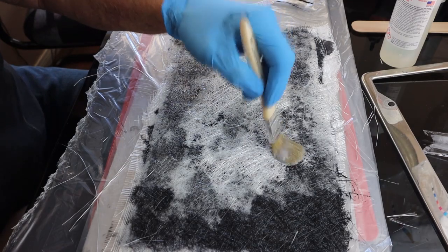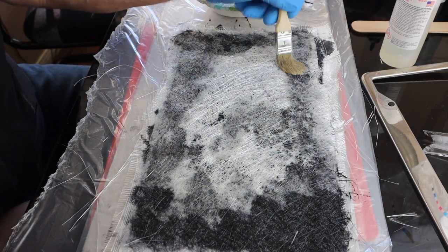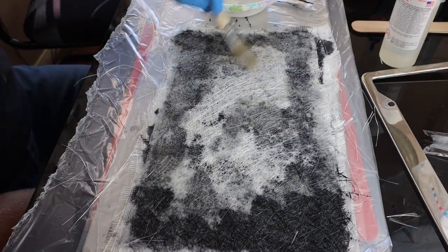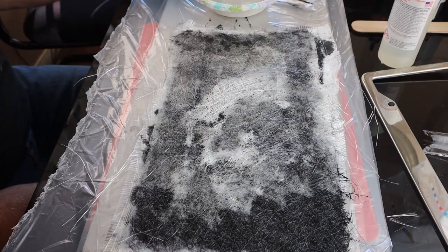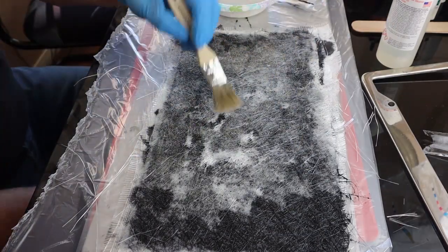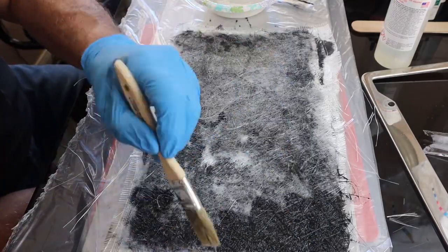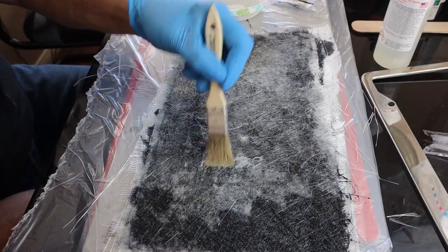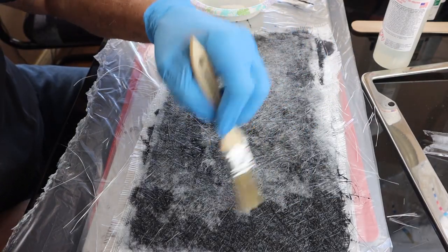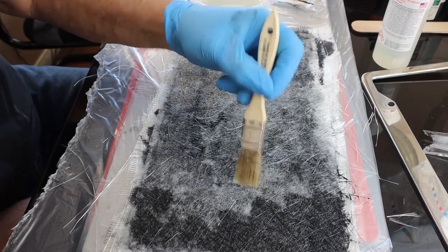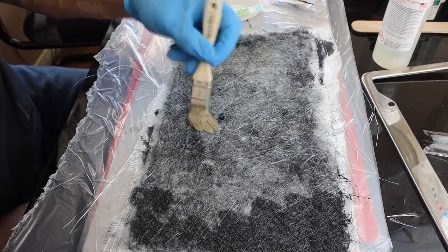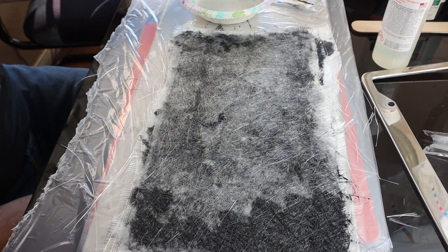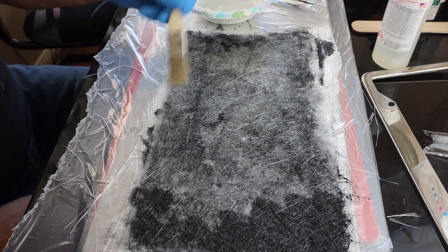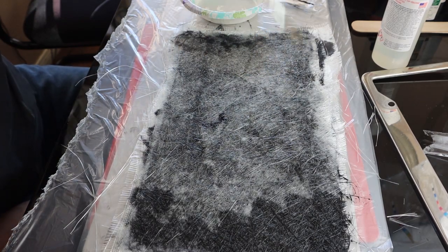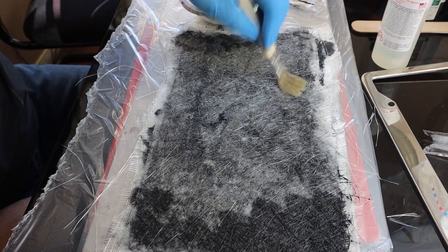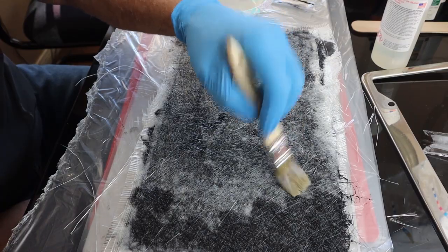And the chopped strand mat really soaks up the resin. Again, you do not want dry plies. You want to make sure this is really wetted out. But you don't want it soppingly wet. And no dry spots or dry marks. You want the resin or the glass to be almost translucent. You don't want any whitish strands, because that indicates that the fabric isn't wetted out enough.